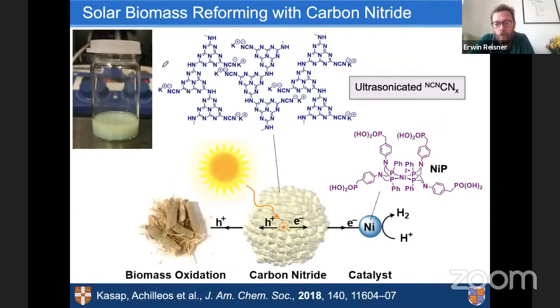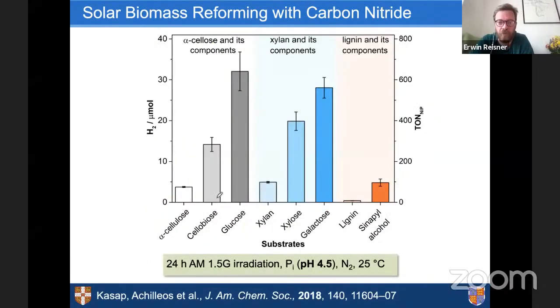So initially, to combine with cellulose, we were fairly unsuccessful because when we made our carbon nitrides, they were still heterogeneous powders that didn't really form a stable suspension. But all we needed to do is really ultrasonicate this carbon nitride. It broke it down into smaller fragments of hundreds of nanometer sizes, and this formed a pretty nice suspension system. And now we could even use just cellulose, polymeric cellulose, under benign conditions to form hydrogen. So the results are shown here.